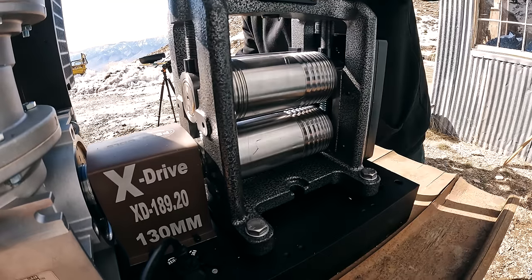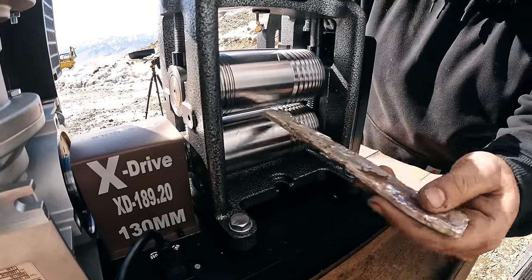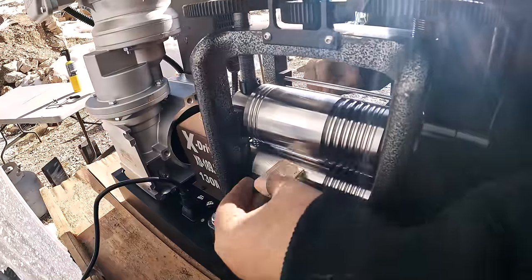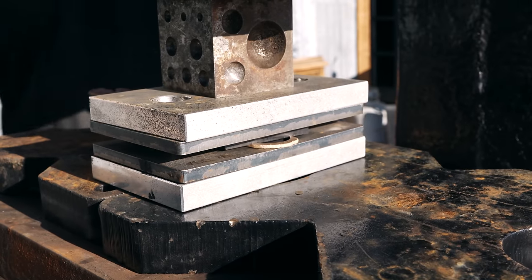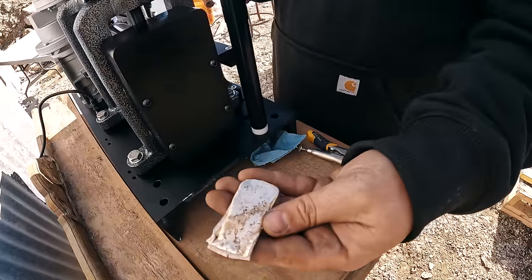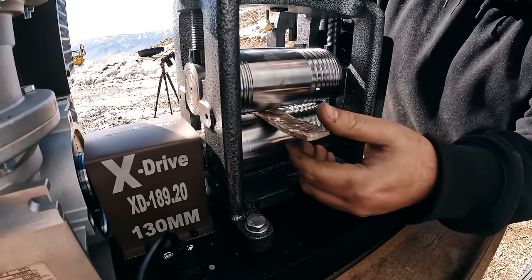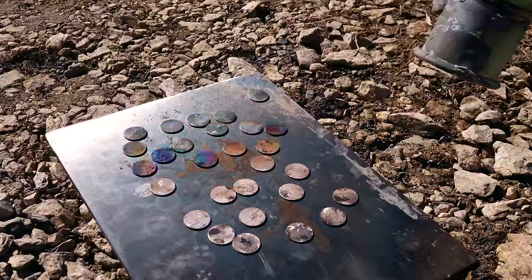You know, first, when we were using the rolling mill to flatten out the silver, we would have to stop, reheat the silver into a glowing red, cool it down, start rolling again, and pretty much every few millimeters, we were having to anneal it again so it could be soft enough to be rolled. And then, before you can press the die into the coin to get your design, you have to anneal again. So it must have just been hours of heating. Our furnaces stayed on all day long as we had different strips of metal being rolled, annealed, stamped, annealed, pressed, annealed, and finally finished.